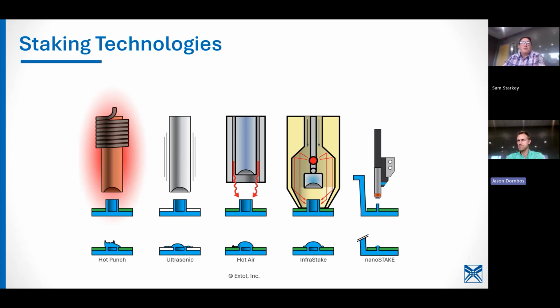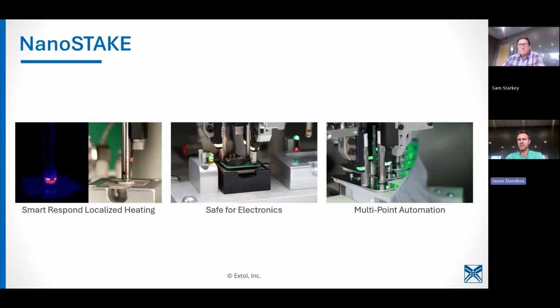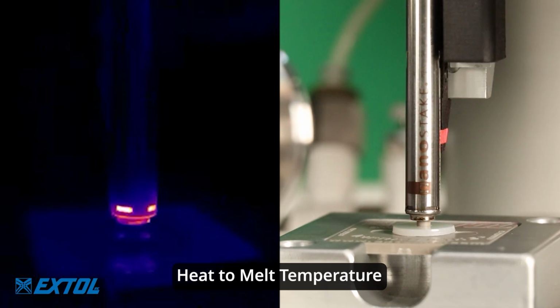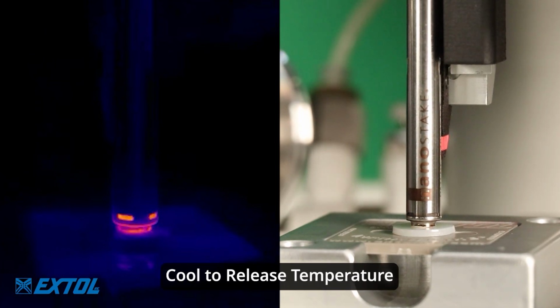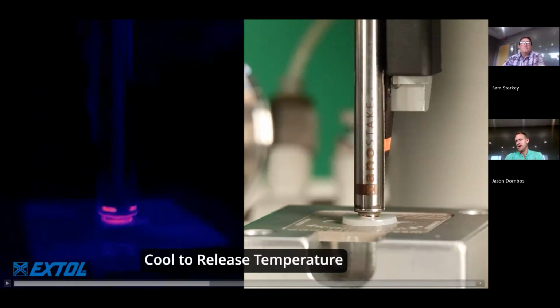Yep. Nano, we are able to control that temperature very precisely. So we can typically, in most materials, get above the Vicat softening temperature, which in most cases is fairly low, to where we're actually able to melt and move those molecules to a point where we're not burning anything else. Even if you look again at this thermal video, you can see right where the temperature is, there's like nothing on it. You can't even see the washer in that thermal video because it's not getting hot.